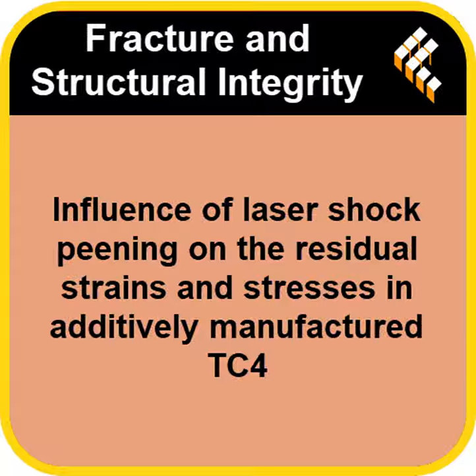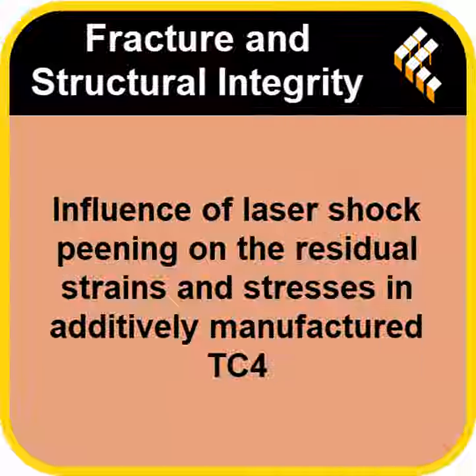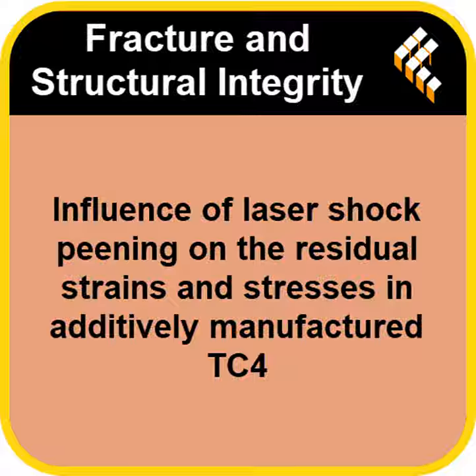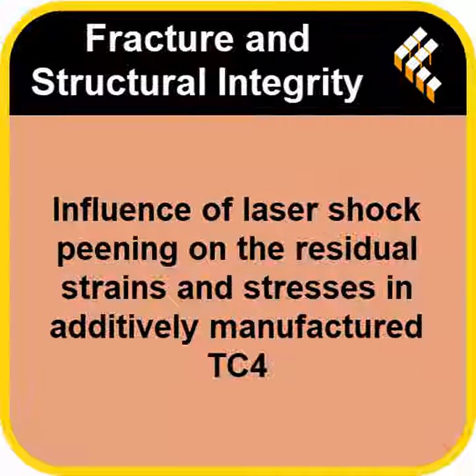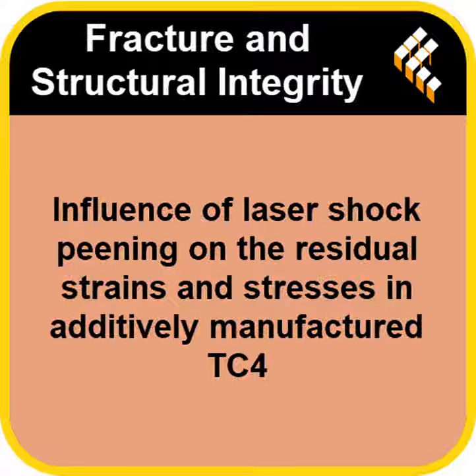And it's not just the stress, is it? The printing process itself can leave other little imperfections. That's right. You often find defects like tiny voids, pores, maybe micro cracks hidden inside. Little bubbles or gaps? Essentially. But maybe even more interesting, particularly for this research, is something called anisotropy. Okay, break that down for us. It means the material isn't the same in all directions. Exactly. Its properties, like its strength or stiffness, can be quite different depending on whether you measure along the direction the part was built upwards, the build direction, or across the layers it was printed on. Because it cools and solidifies layer by layer, the internal structure itself has a directionality baked in. Which must affect how it responds to treatments later on.